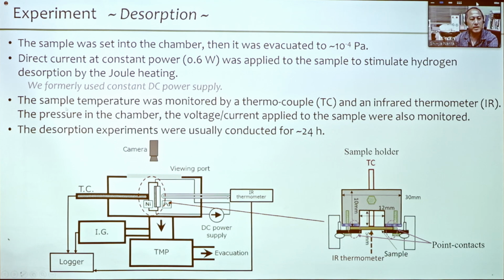So then the sample temperature was monitored by a thermocouple and the infrared thermometer, and the pressure in the chamber and the voltage and current applied to the sample were also monitored. And the desorption experiments were usually conducted for 24 hours. So these are some details of the sample holder. The sample is fixed here, and electric power was applied through this point contact. Then the temperature of the sample was measured by the thermocouple here and the infrared thermometer here. And here you can see the camera, and the sample was monitored by the camera through the viewing port.